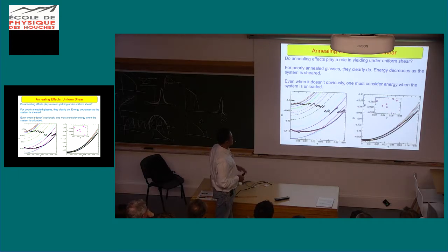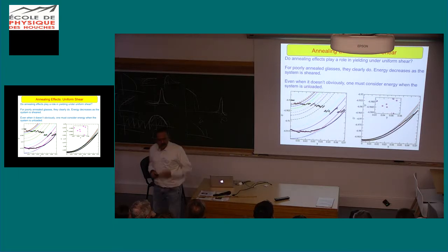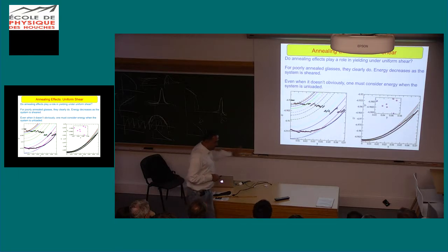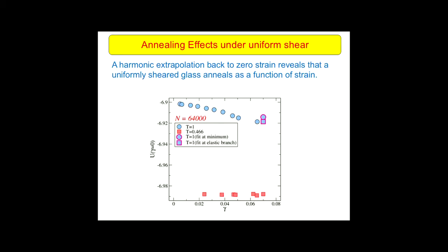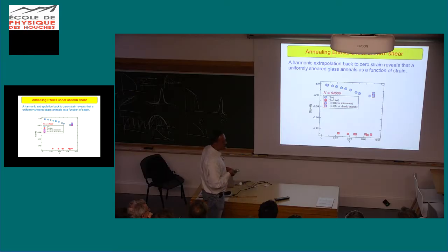And this is not something that I would hang my hat on, but this is something to put before this audience to think about and talk about. Even when one does uniform deformation, if one looks at the energies, certainly for the poorly annealed glass, the energies go down, and this is not a good way of talking about it. So what one should look at is the zero strain value of the energy, and we make an effort to estimate what those are, and those energies clearly do decrease. So in other words, even under uniform shear, there are annealing effects going on.